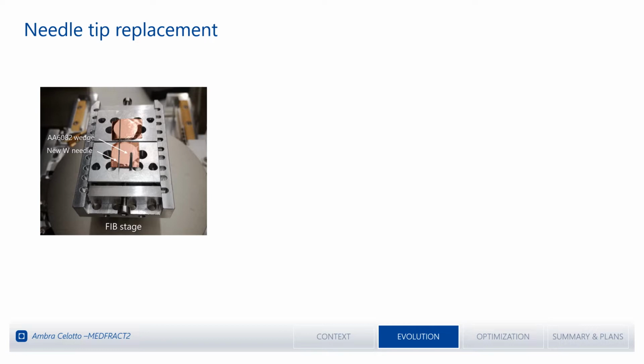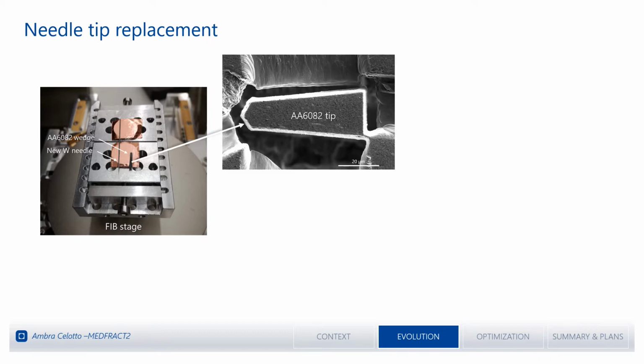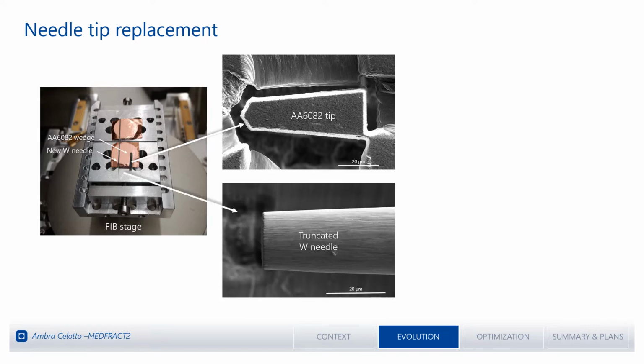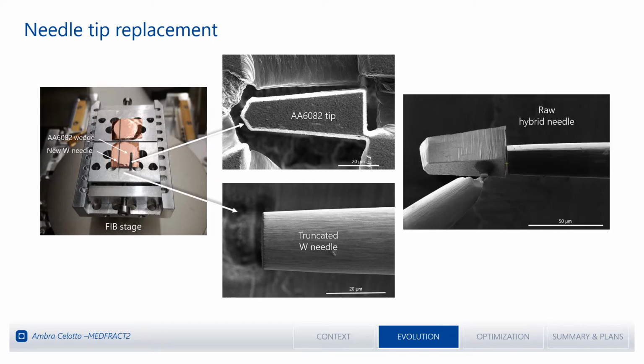In practice, we take a new tungsten needle and put it in the FIB stage together with a piece of filler metal that has been previously mechanically polished. Using the microscope, by FIB milling, we take out from this aluminium wedge a tip shape of aluminium. In the same way, by FIB milling, we truncate the tungsten needle. And by using the micromanipulator, we lift out the aluminium tip and put it in contact with the surface of the tungsten needle.